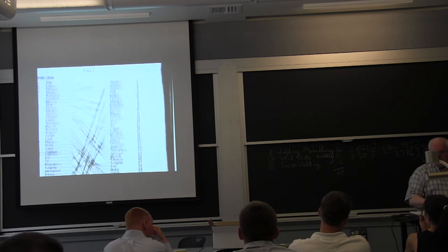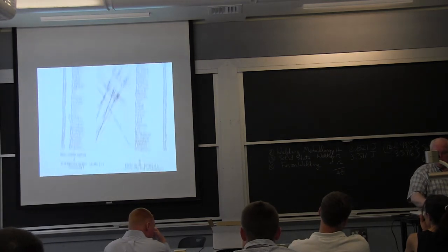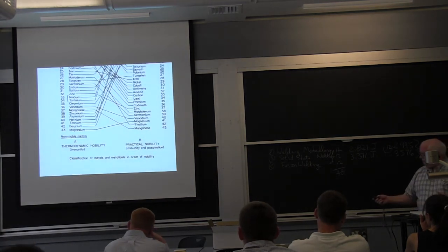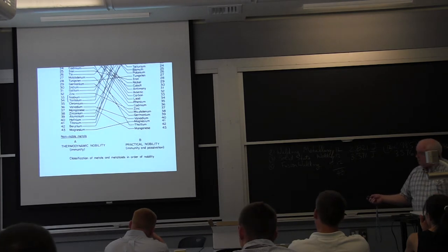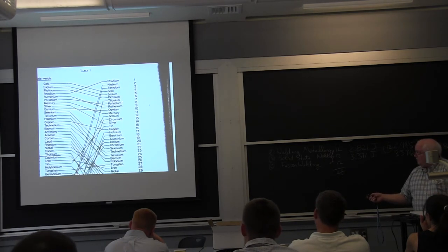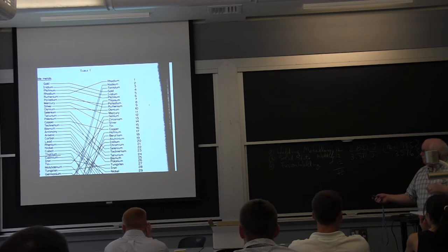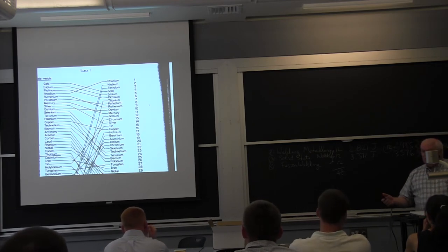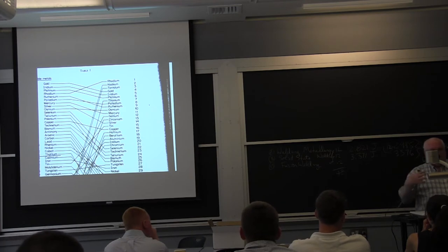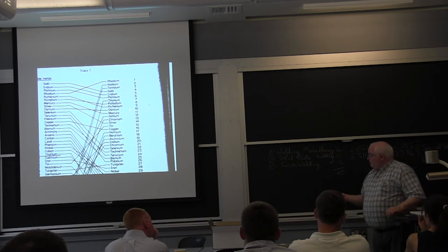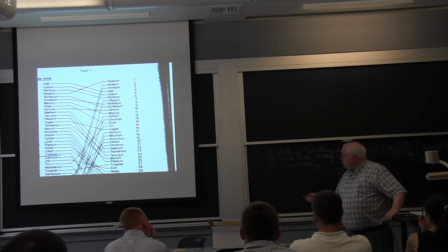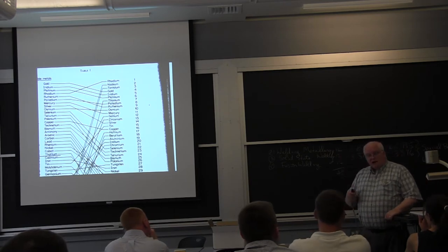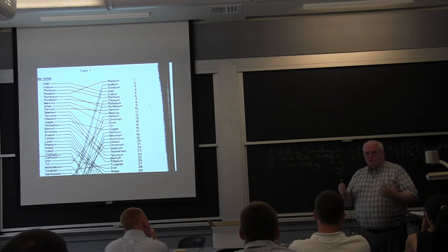Okay, so you can talk about thermodynamic nobility and practical nobility, and practical nobility is what really counts, but the problem with practical nobility is if you lose your protective oxide skin on some of these things that are the best, like titanium, I told you, titanium you can dissolve its own oxide above 900 C. The other thing, early on they had some very serious explosions where titanium was being used when they first developed it,